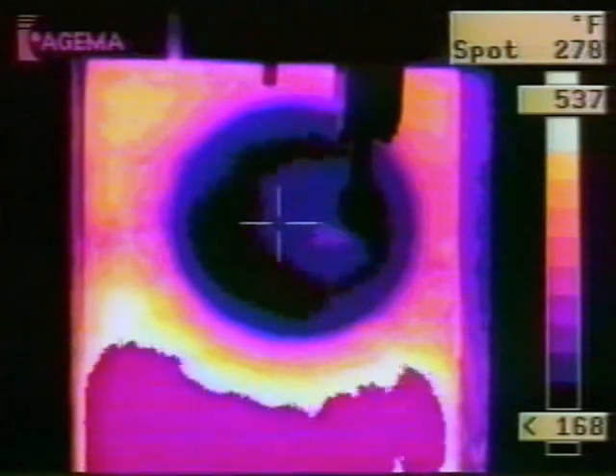Properly spray the die. Although a flood of die lube can quickly cool the surface of the die, an atomized spray has shown to provide a deeper, longer-lasting cooling effect. Atomization of the die lube is an area that should be addressed for each die. The trend to flood the die may allow quicker cycle times, but should be compared to the extra expense of wasted die lube and parts rejected due to the quality problems that may be caused by improper spraying techniques.